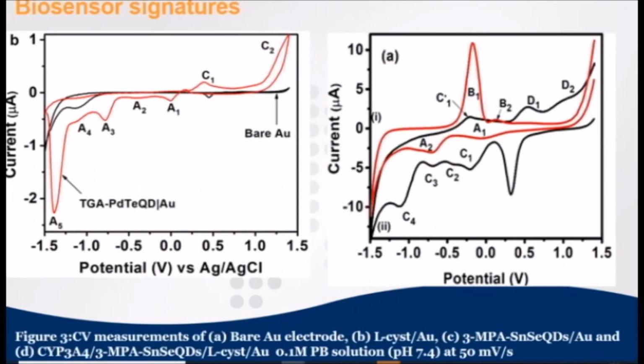Another important point is that we moved from the L-cysteine on to the quantum dots on their own, and we are comparing these quantum dots with the bare electrode before combining the enzyme on top. Looking at our bare, the bare is the black line still, and the red is the quantum dots. We can see that the quantum dots have several redox peaks. We call them redox: it's oxidation and reduction. The quantum dots exhibited several redox peaks, which are attributed to the palladium, tellurium, and the stabilizing agent.